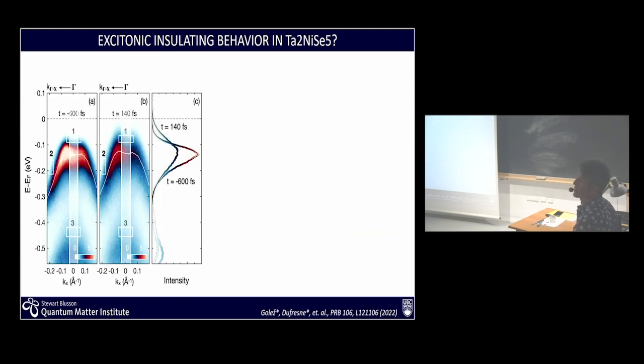And so that's where we come in. What we do here, we look at our photoemission intensity before the pump comes in, so negative delays, and then after the pump has come in. Here, we're just plotting the data from the gamma point, a single spectrum. And what you can see, comparing the no pump with pump, is again a small shift of a peak position.